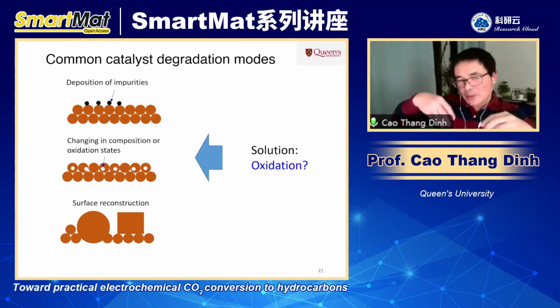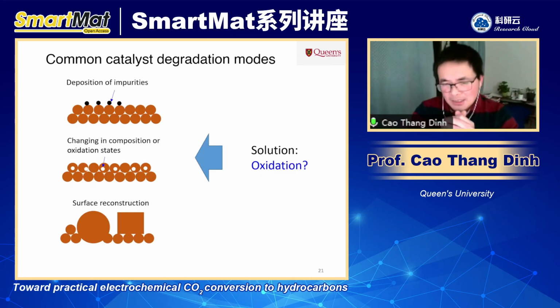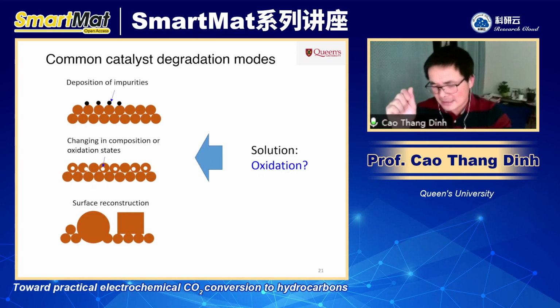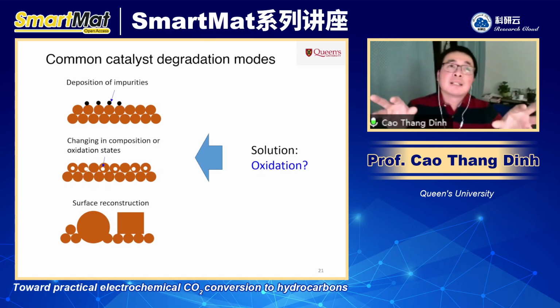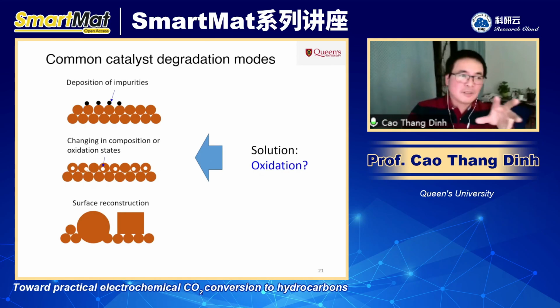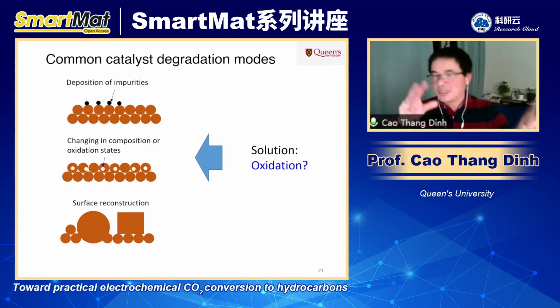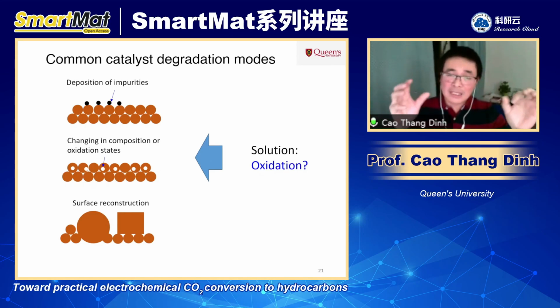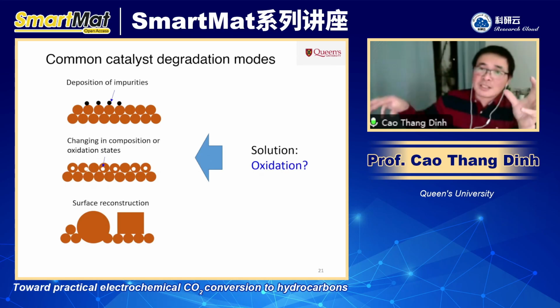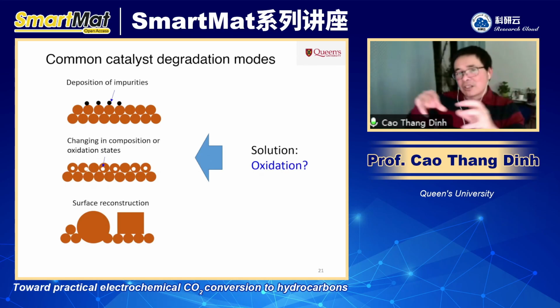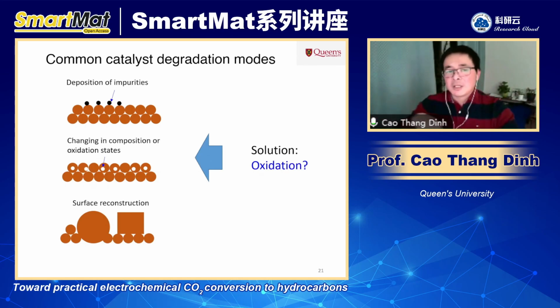So when it deposits on the surface of your catalyst, not only does it block your active site, but it also creates a site for hydrogen evolution, which is the competing reaction. We don't want that. Now, the second one depends on the nature of your catalyst. If it's an oxide, you have a different oxidation state in your catalyst. So during the reaction, the oxidation state of the catalyst can change because it's under reducing condition.